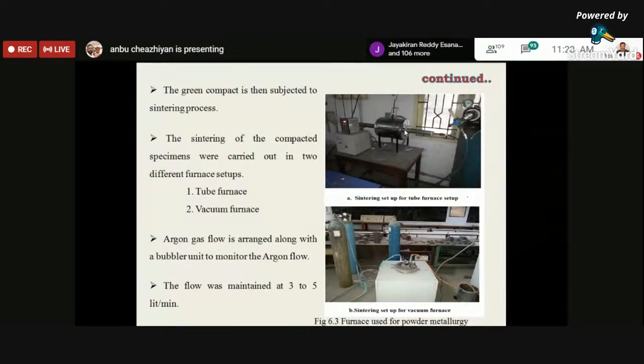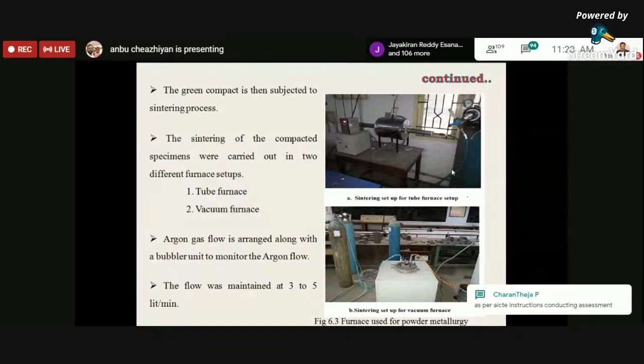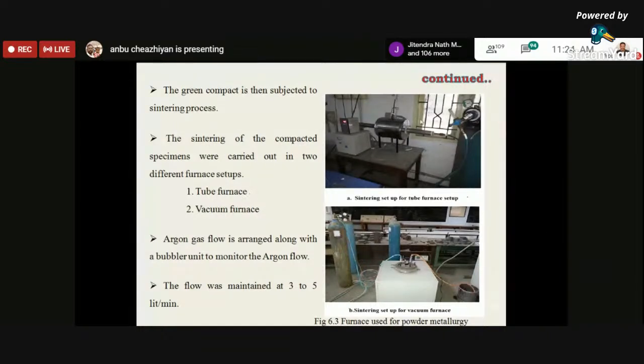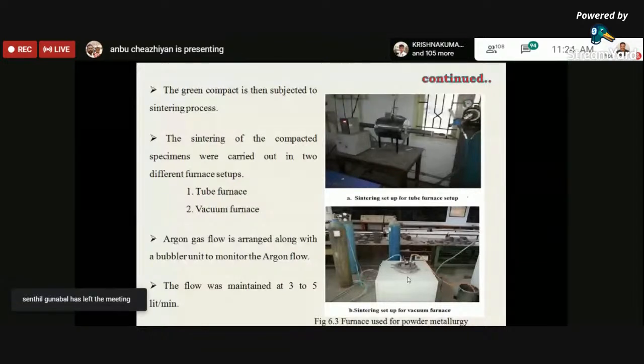So we're going to keep a material in that, and we are sending argon gas into that material. So that is a tubular furnace, and next we have the vacuum furnace. So this is the thing. Inside that we are going to keep the material. So we are having an argon atmosphere in a closed environment. Here we have sent 3 to 5 liters per minute of argon. From the literature we have taken that 3 to 5 liters per minute.